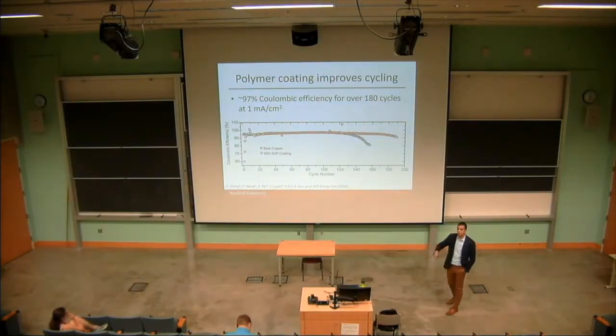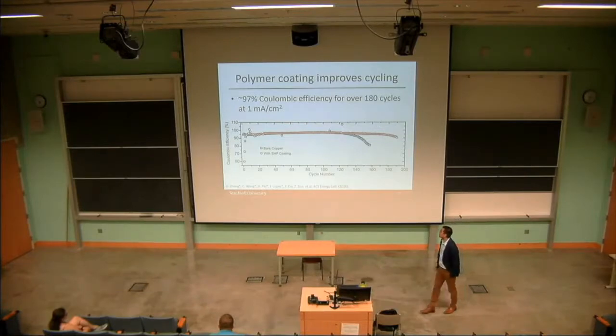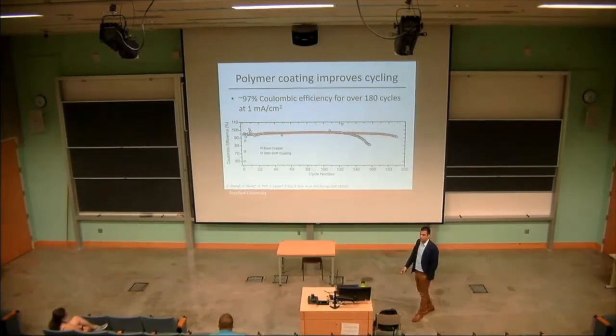Looking at the efficiency of these cells, so this is not capacity anymore, but instead coulombic efficiency, so how much lithium we can pull out after we deposit. Ideally it would be 100%, typically it's not. And you see here, though, we maintain cycling stability for a longer time. The cell begins to die due to buildup of that resistive SEI that forms, and we delay that by about 20 or 30 cycles here with high efficiency. And so this polymer coating really is not only helping to improve the morphology of the lithium, but helping to improve the stability of these cells over time.